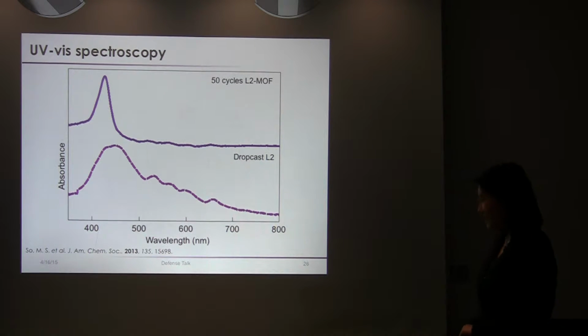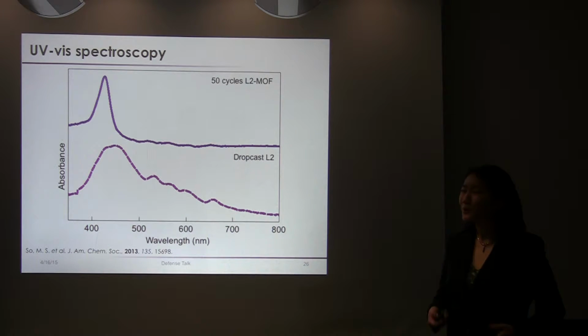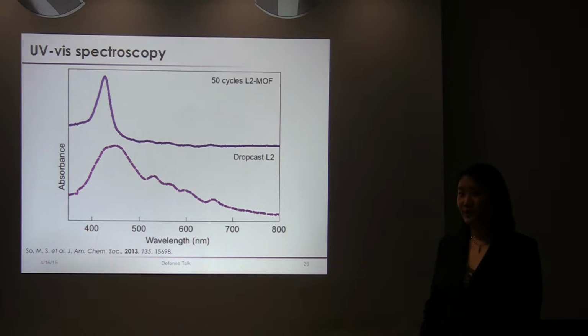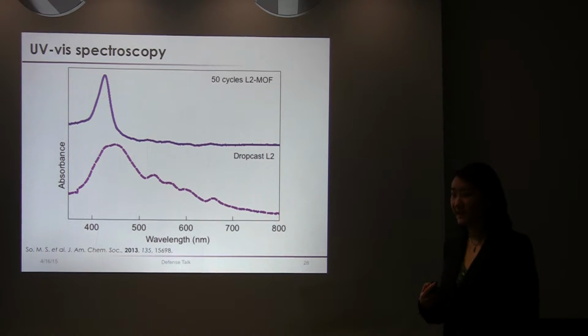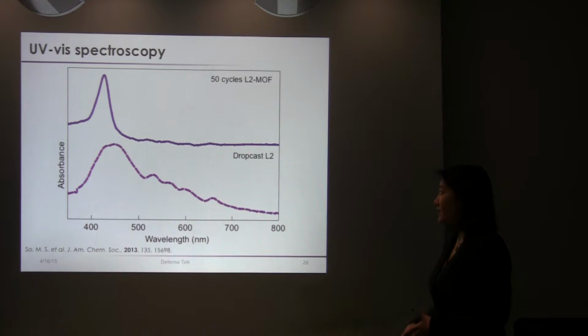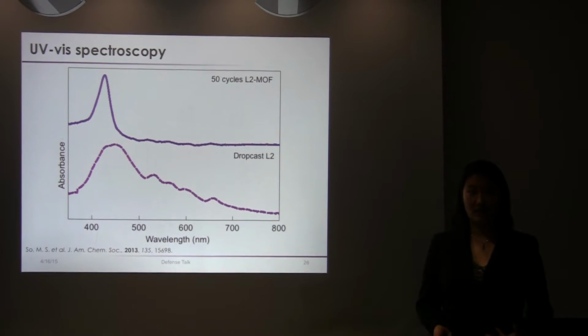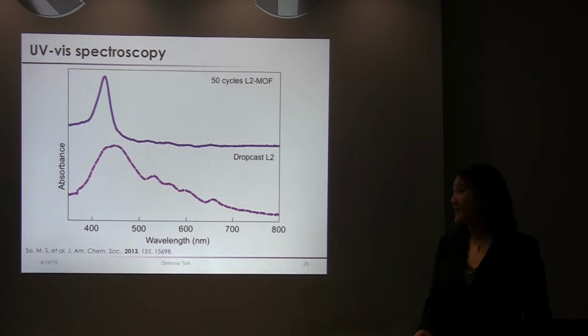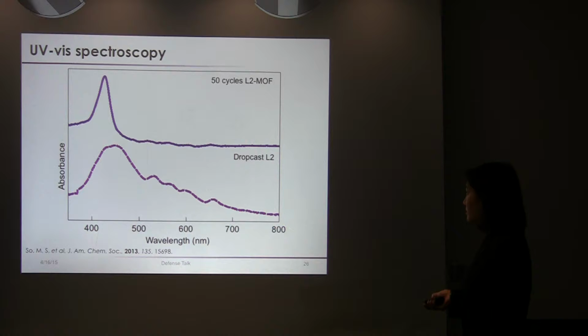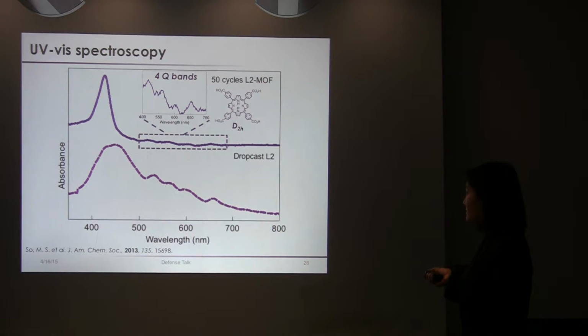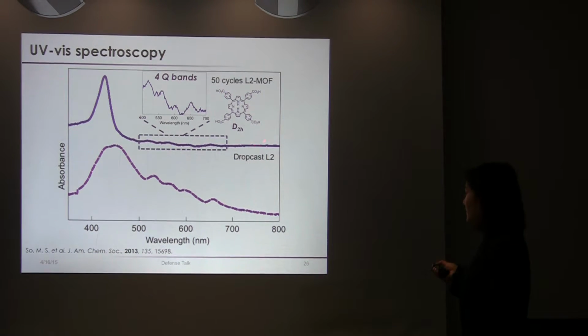All right, and another thought that I had for this project was that typically incorporation of free-base porphyrin linkers in bulk crystals is a very difficult task because the acidic conditions as well as high temperature conditions that are used typically spontaneously metallate the porphyrin linkers. And so I thought that using a much more mild reaction condition in layer by layer growth, this problem would be circumvented. And so I essentially formed MOF films of L2 MOF. And what I saw was that 4 Q bands were retained. And this corresponds to a D2H symmetry, essentially a non-metallated porphyrin in the MOF film.